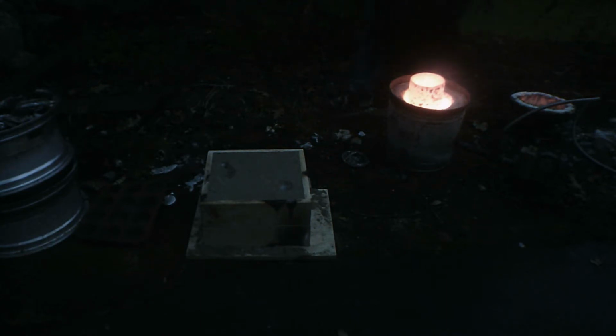Now before I can do that, there's a whole bunch of molten aluminum in here, and any impurities in the aluminum will have risen to the surface, so they need to be scooped out. That stuff is called slag or dross, and if that got into your casting, that would give you a bad time. So removing as much as you can is a very good idea. I'm just using a piece of angle iron here. Probably using steel in molten aluminum will corrupt the metal a little bit, but not enough to make any noticeable difference for me.